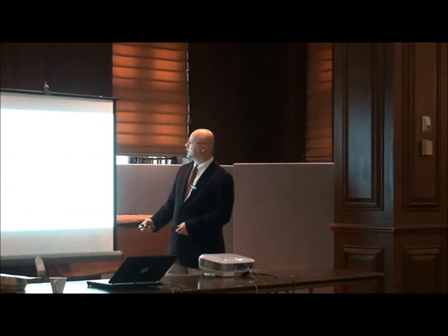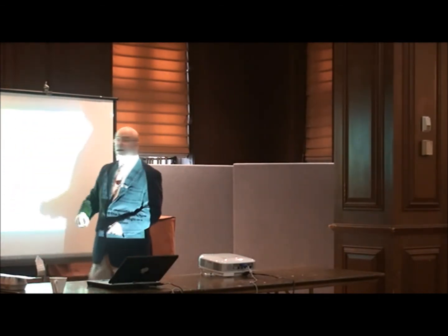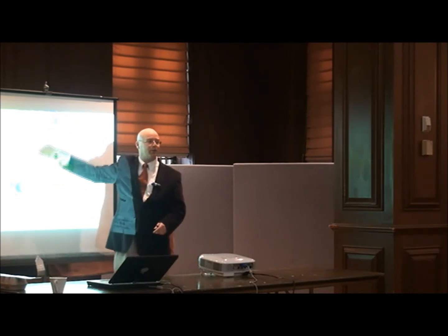We actually had to get a little more nuanced. If you take the analysis in all the directions on the surface here, you end up having to interpolate points. If you just pick a direction on the surface, you've digitized the surface. So when we've sampled our surface, we've either oversampled it, so we've got overlapping spots that we've measured, or we've put the spots we're measuring adjacent to each other on the surface, or we've got some space in between them. Or if we have a raster scanning type instrument and we're in a hurry, we've put some space in between them in this direction, and we've put a lot of space in between them in this direction. And now you don't have a characterization of the 3D topography anymore. You have a series of profiles on the 3D topography, but the software is going to treat it as if it was a characterization of the topography on the surface. So those are things to watch out for as you're doing the measurements.